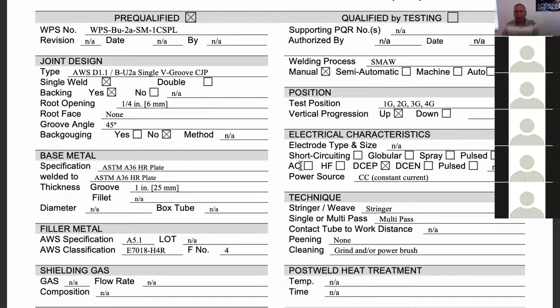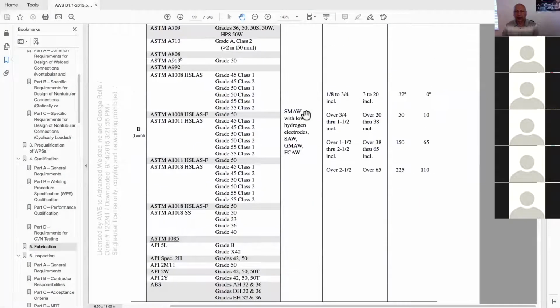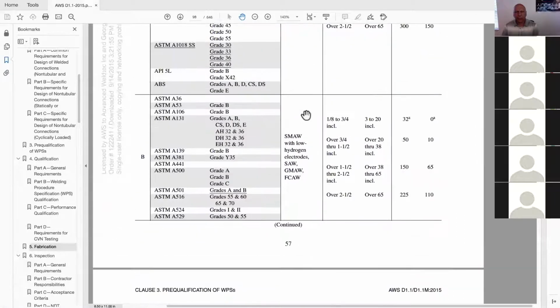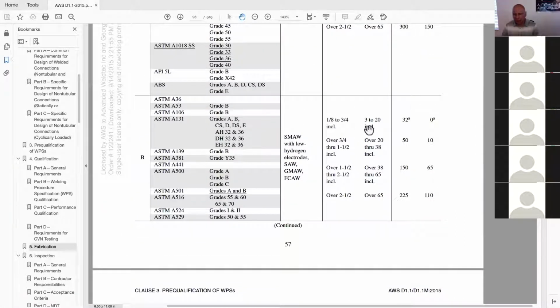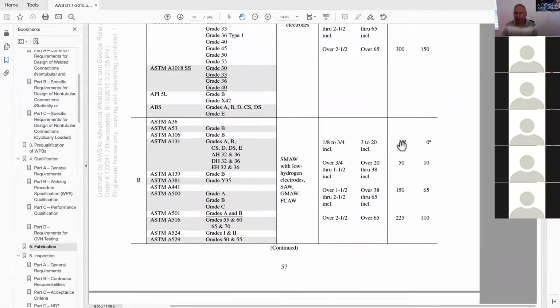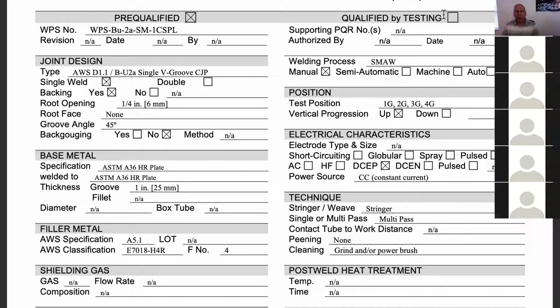In fact, actually, that should read 50 degrees if I'm not mistaken. So we may have to edit that, because when we go back to the preheat interpass temperature, category B steels, A36, over 3/4 inches require 50. Yeah, a 50 degree minimum preheat, not a 32. If we were doing a 3/8 test plate, that would be only 32 required. We need 50. Nevertheless, we never fall below that. Pretty rare. It goes into the 40s here in our area in California.